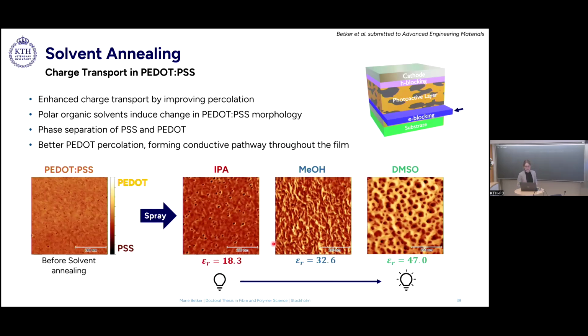All right, so similar as for the silver nanowires, where we already talked about percolation, here we used solvent annealing to enhance the percolation of the PEDOT in our electrode. So on the very left side, in orange here, this is the sprayed electrode before. Pure PEDOT-PSS, you see it's really intermixed, and the scale here actually means that the darker the colors, the more PSS we have, and the brighter the colors or more yellow, this is representative for PEDOT, for the conductive part. And here we see the results after the solvent annealing.